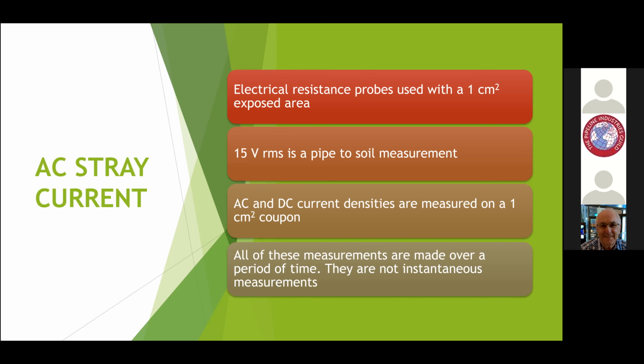So that means that if you had a coupon of 1 centimeter square and it corroded, its surface area would decrease, so its resistance would increase. And by doing some fancy measurements, we can calculate what the corrosion rate is. And with the electrical resistance probe, you can also measure the actual corrosion rate, the AC and DC current densities, and the ratios between the AC and DC current densities. So corrosion probes are one way to deal with it.